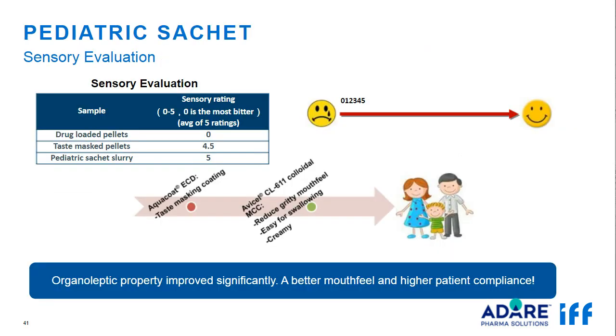Taste evaluation was done by a taste panel of 5 people. Paracetamol uncoated pellets received a score of 0, indicating the most bitter sample, and pellets coated with Aquacoat received a score of 4.5, which was perceived as better when tested in the suspension, described as a creamy and easy to swallow formulation, with a score of 5.